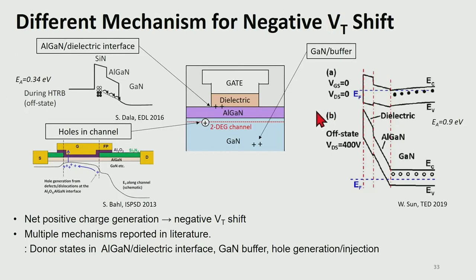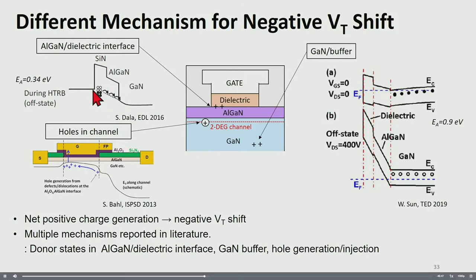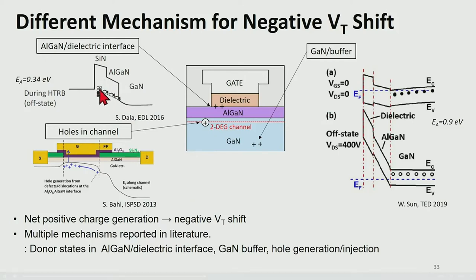So there has been extensive research to understand the mechanism of this negative shift. One possible explanation is that the donor state at the AlGaN-dielectric interface can be activated under gate or drain voltage stress. This effect can provide a positive charge effect in this location, which attracts more electrons at the AlGaN-GaN interface. So this can cause a negative VT shift.